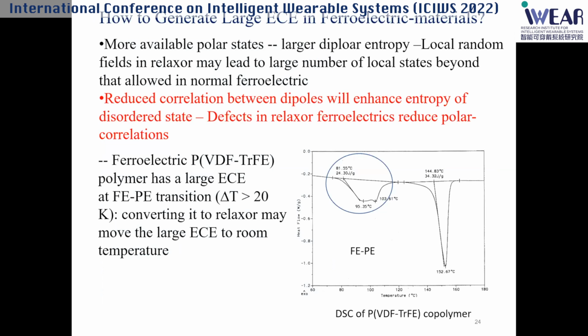So we looked at, for example, PVDF-based polymer. Once we thought about this, it's very simple — you look at this material, and between the ferroelectric and paraelectric transition, the heat of transition is 24.3 joules per gram, which is pretty large.